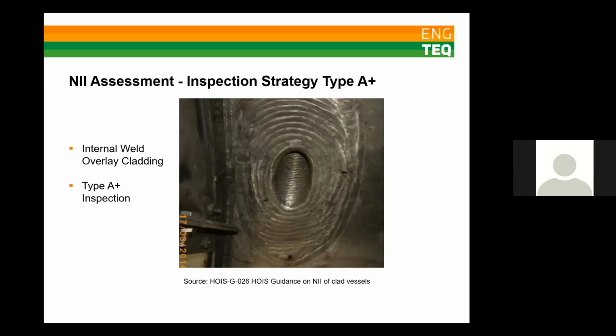So the coarse grain structure can limit the effectiveness of angle beam ultrasonic methods and their ability to detect stress corrosion cracking in the cladding. The coarse grain structure tends to scatter and attenuate ultrasonic energy. Therefore, the detection and sizing of cracking at the cladding inner surface is challenging on weld overlay cladding. In addition, the uneven internal surface due to the individual weld beads can cause increased reflections when using angle beam methods. The use of angle beam compression wave DMA probes gives lower levels of backscatter than angle beam shear waves, but stress corrosion cracking detection is still unlikely to be reliable.